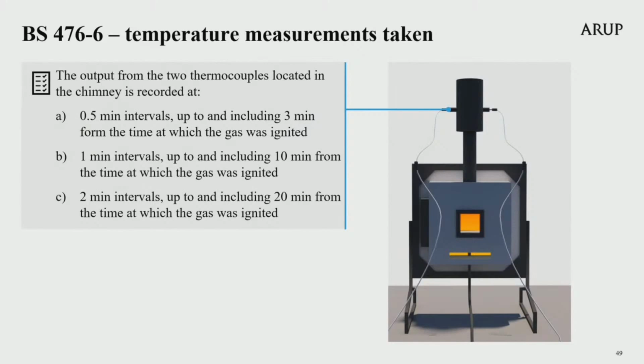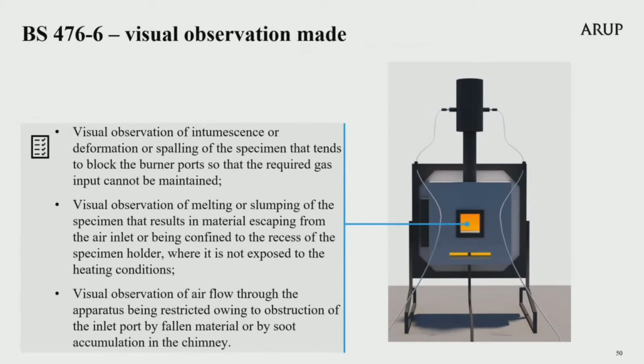The output from the 2 thermocouples located in the chimney is recorded at some specific intervals we need to discuss. At 0.5 minute intervals up to and including 3 minutes from the time at which the gas was ignited, and this is then converted to a parameter called S1. At 1 minute intervals up to and including 10 minutes from the time at which the gas was ignited, and this is then converted to a parameter called S2. 2 minute intervals up to and including 20 minutes from the time at which the gas was ignited, which is then converted to a parameter called S3. All the visual observations should be recorded during the test as observed through the window, as I have already explained.